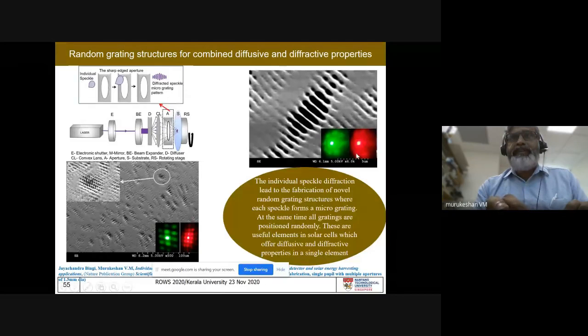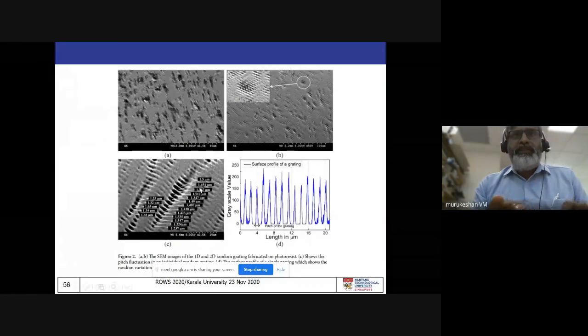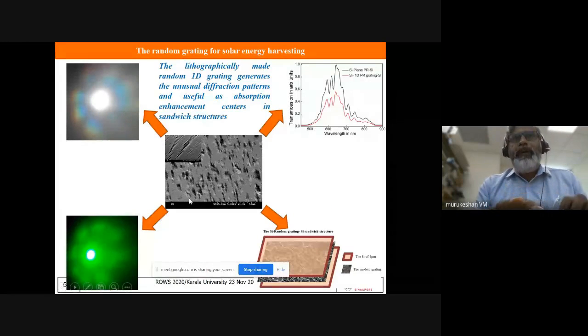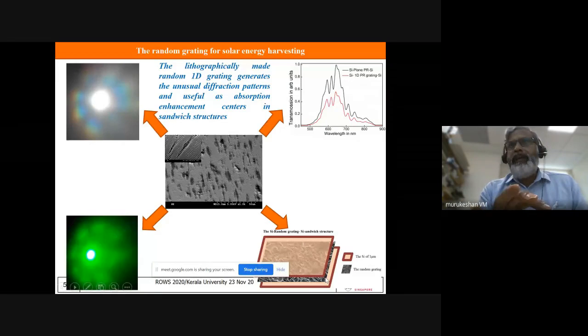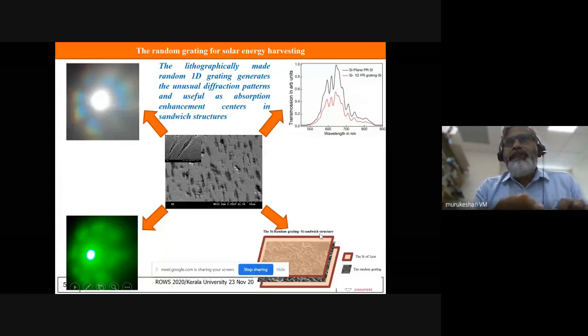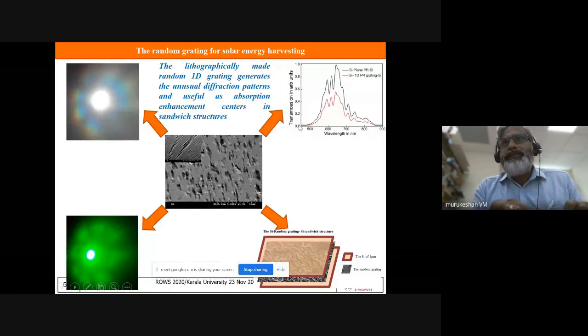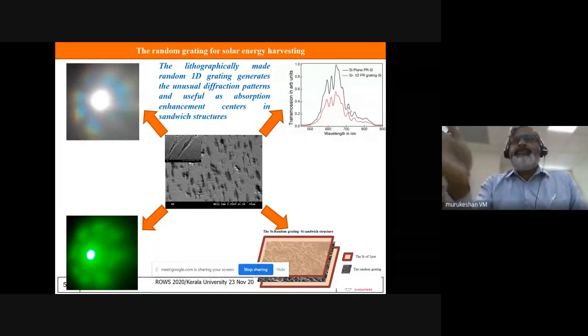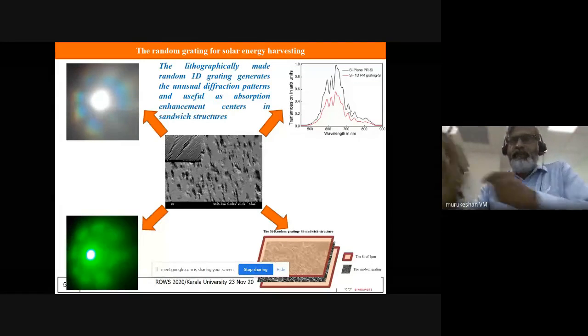Needless to say, you can see the diffraction pattern that you can get using different light wavelengths when you use one-dimensional as well as two-dimensional grating structures. And this is a very, very interesting pattern, and it has been applied for some of the applications. And this is just to show that this is really random, because the pattern dimension is actually varying. But all these are in micro scale. And if you put this structure in between two silicon surfaces, you can see here, that is silicon, random grating, silicon sandwich structure. And we found that the transmission is reduced to a great extent, okay, 30–40%. And that is the way we can improve the absorption. And this is used for solar energy applications, which is another work we have done, okay.